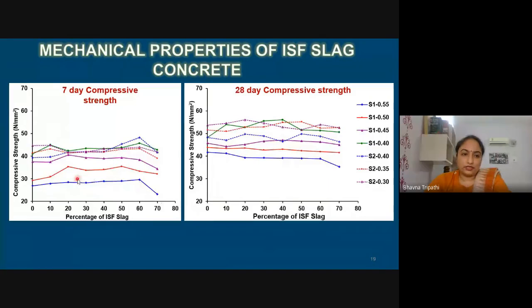If we start from the lowest strength mix, then this mix is having a water cement ratio of 0.55. Here is the legend. And we can see that most of the mixes have similar to control, control is the 0% mix, similar to control or higher than control compressive strength, except for the mix which has ISF slag up to 70%. The 28-day strength is more stabilized. There are less ups and downs. So the strength of control mix has also been achieved.